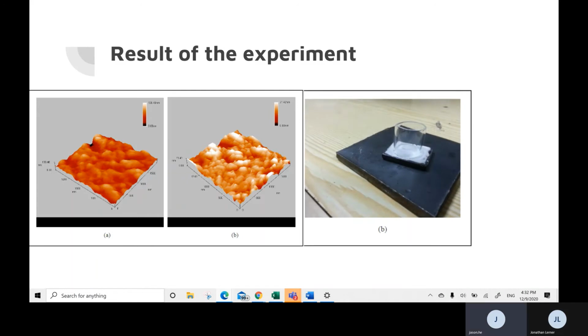The two mechanisms of bonding glass metal were achieved. The first mechanism was performed by laying all joint parts into a furnace before pre-oxidizing the metal surface. It was found that the bonding is very weak and is only about 0.1 to 0.2 megapascal for all types of metal tested. The second mechanism of the bonding glass metal is by pre-oxidized metal surface before putting the metal and glass into the furnace. It ends up the maximum bond strength between the glass tube and the metal sheet is 2 megapascal, which outperform its unoxidized counterpart significantly.